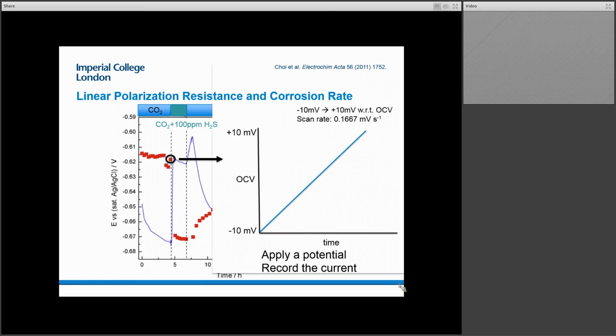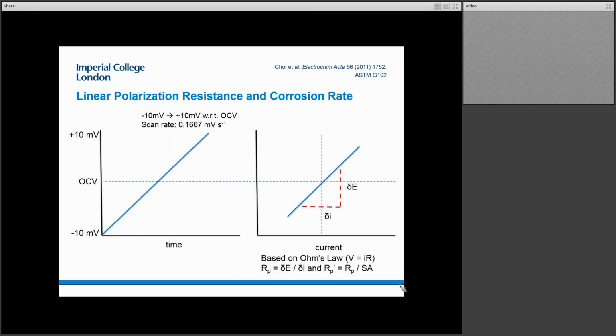So the application of corrosion rate, we're going to step back to how we get to the point where we can make this plot, is a result of basically, at short time intervals, making perturbations, very, very small ones that are expected to be reversible, where we're perturbing our system in terms of the potential. And again, we're applying the potential and recording a current. And the idea here is that if we make this very small perturbation in the potential and record the current, we'll have a relatively linear behavior because it's a small differential space.